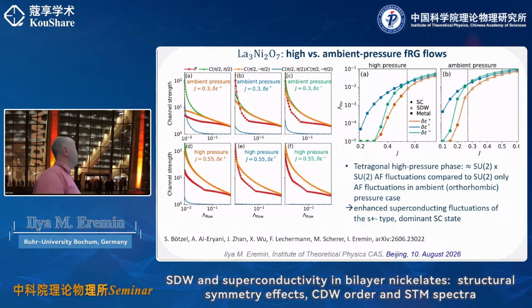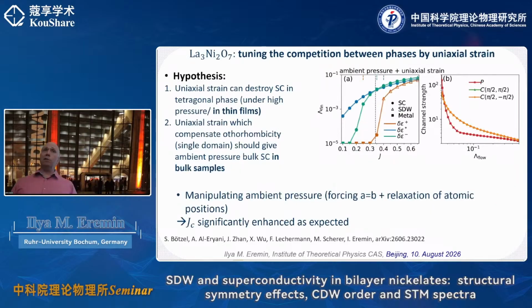And the prediction is that now you can make a hypothesis. Given the current situation of the experiment, you can do two types of experiment. You can start from the thin films, which we know are tetragonal, but now you don't apply only compressive strain, you also apply uniaxial strain. If you apply uniaxial strain, you expect that it should become magnetic, because you will be suppressing superconductivity, because the system will no longer be tetragonal. Or you can try another experiment where you apply a strain to compensate the orthorhombicity, so a compensating strain. It's more challenging given the structure of these bilayer nickelates, but in theory you can do it.